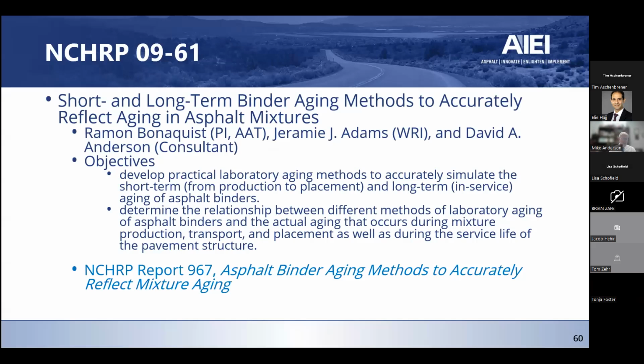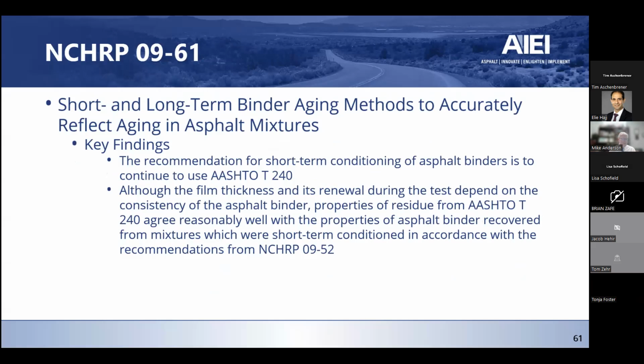Work done by Ray Bonnequist with Advanced Asphalt Technologies, with Jeremy Adams at Western Research and Dave Anderson as a consultant. Basically they were looking at short-term and long-term aging of binders, the procedures we use and how they correlate with what we see in the mixture field. The outcome was that the RTFO that we've been using for some time, basically since SHRP and the PG system came about, is really about as appropriate as we can get. It reasonably correlates with the short-term aging that we see during production of asphalt mixtures.